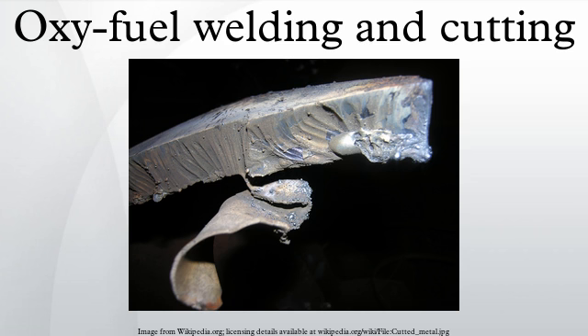Gasoline. Oxy-gasoline, also known as oxy-petrol, torches have been found to perform very well, especially where bottled gas fuel is not available or difficult to transport to the worksite. Tests showed that an oxy-gasoline torch can cut steel plate up to 0.5 in thick at the same rate as oxy-acetylene. In plate thicknesses greater than 0.5 inch the cutting rate was better than oxy-acetylene. At 4.5 in it was 3 times faster.